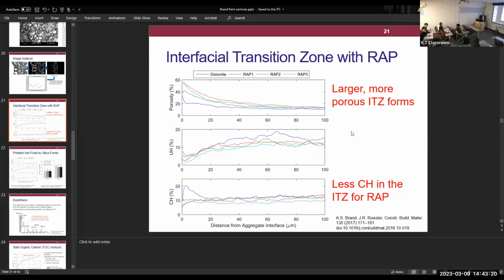Have you ever compared the ITZ for samples before and after test? After which test? Maybe some comparative test. Yes and no. It would be difficult to do this type of characterization because we'd see a lot of micro cracking, and therefore a skewed measurement of the porosity. We'd have to somehow threshold out cracks. I don't know if anyone's actually done that work. That's an interesting idea, actually. But you could do imaging of, let's say, a fracture surface.